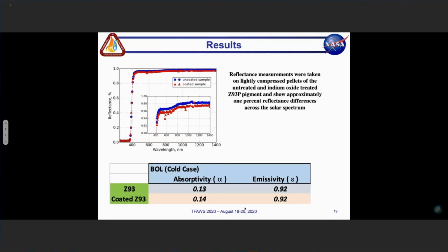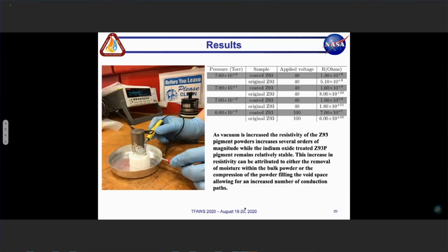We had a very, very small change in the reflectance measurements. And in terms of your absorptivity and your emissivity coatings, we basically saw that we really did not change the optical properties. I think everything we see in terms of those absorptivity, emissivity values are within the error of measurement. So moving on, one thing we were able to do is find out what happens in vacuum.